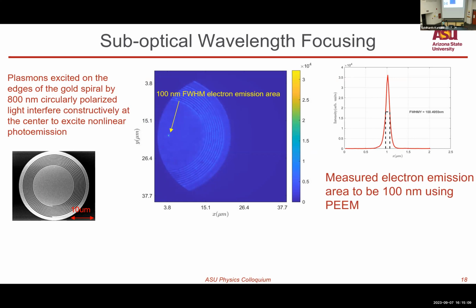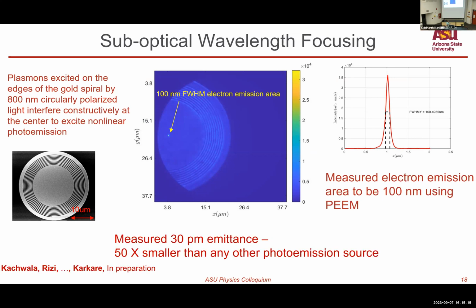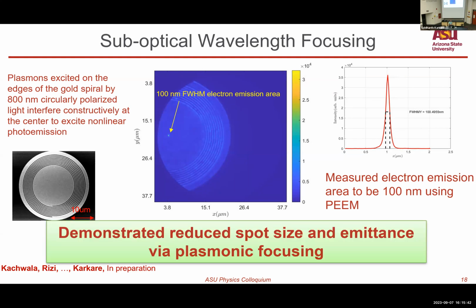If you measure the full width half max, it's 100 nanometers. Now, that basically results, we also measured the energy spread. Of course, the energy spread means transverse energy is several hundred millielectron volts because we're relying on nonlinear photoemission. It's not optimized for a particular excess energy. But if we converted both of these to emittance, it's emittance of 30 picometers, which is 50 times smaller than any other photoemission source. Which is extremely exciting. And we have recently demonstrated this reduced spot size and emittance via this plasmonic focusing.